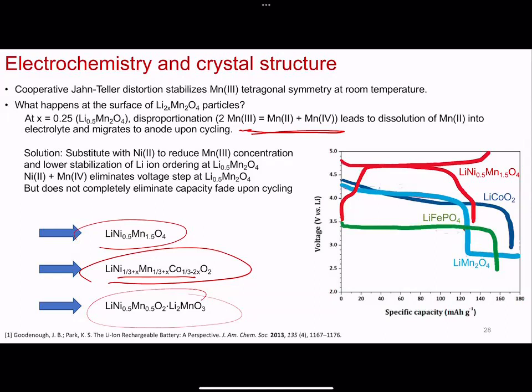So then you kind of have to balance. I have to balance manganese dissolution, but I also want higher thermal stability. So there's a balance. That's what people have been trying to do, right? People have been actively trying to engineer compositions as well as morphologies and microstructure so that you come up with a balance where you get the best of both worlds, right? Either you make some complex morphologies like a core-shell type structure with different compositions. Maybe you tune the particle size so that you increase diffusion and you stabilize the surface area so it's not too small, not too big. So there are countless strategies to try to stabilize this composition where you increase the nickel content.